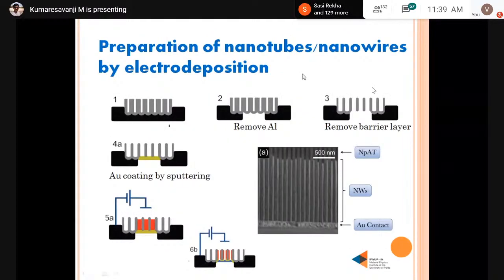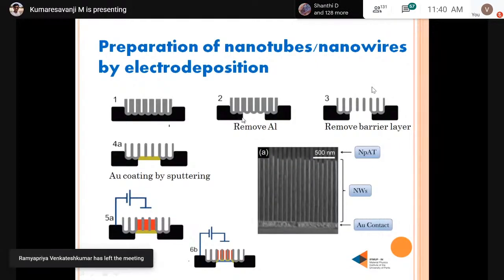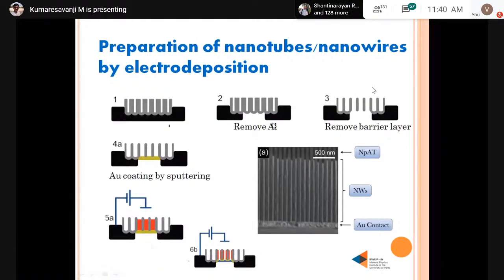So here I show how our colleagues are making nanotubes or nanowires by electrodeposition. This is our prepared nanoporous template, right? Here is the aluminum foil, the alumina layer and nanopores. First, for the electrodeposition, we remove the aluminum by chemical etching. Then we remove the alumina layer also by chemical etching. So now we have a pore in the nano template.